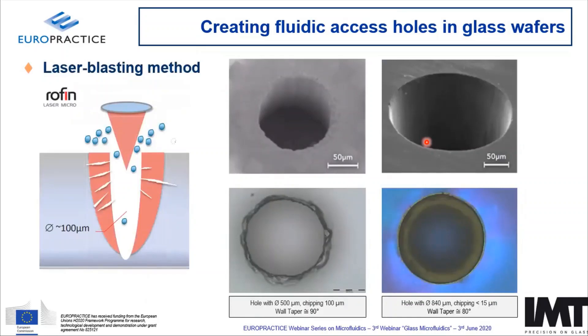On a wafer level you can also do laser drilling. Lasers have won a lot of market in this area. You can go from nanosecond, picosecond, to femtosecond lasers. The faster the pulses, the more accurate the hole you drill, but the more expensive your wafer becomes. You can clearly see nanosecond versus picosecond holes — picosecond has much less chipping, due to the generation of micro cracks in ablation processes. However, pico and femtosecond lasers have much longer processing times and are consequently more expensive. Don't forget — it is hole by hole, so if you're having 200 holes, that's going to take a long time.